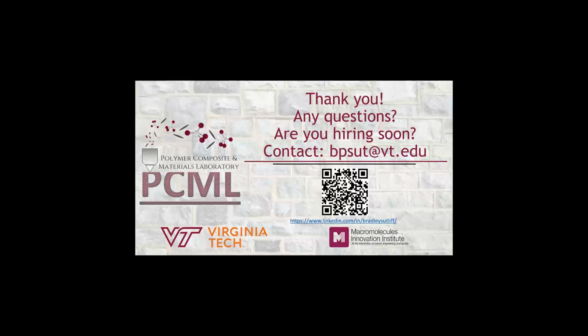So that's a good point. The nice thing about working with cellulose nanocrystals that are never dried is they do stay quite well dispersed. Cellulose nanofibrils, on the other hand, those are just pure flocs. Some of the data I was hoping to share today, but didn't quite get the paper submitted in time, is on dealing with those flocs and how you can process to get around it. Bentonite clay is interesting to work with, it's just not something we have super readily available, but it would be interesting to look at.